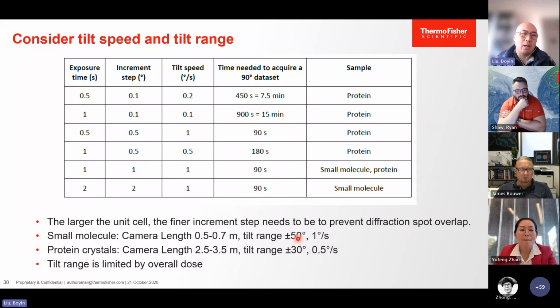So in general, the larger the unit cell, the finer the increment step needs to be to prevent diffraction spot overlap, because you're sampling a wedge of the sample. For a protein crystal with a bigger unit cell, there's so much information in there. So sometimes if you tilt too fast, you're going to have overlapping information. So in that case, you have to slow down.